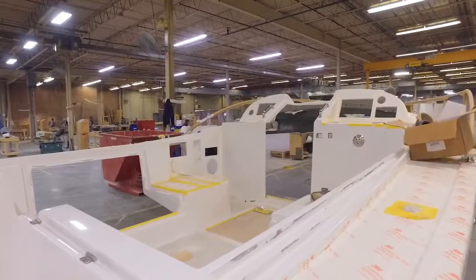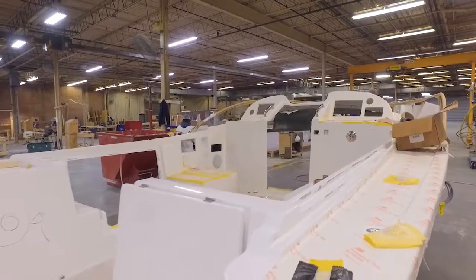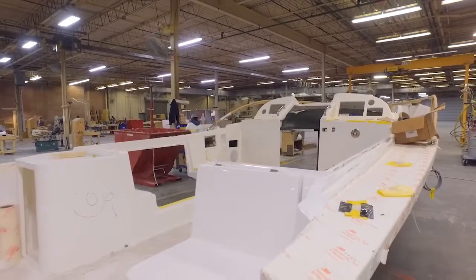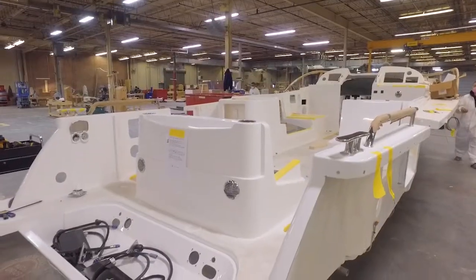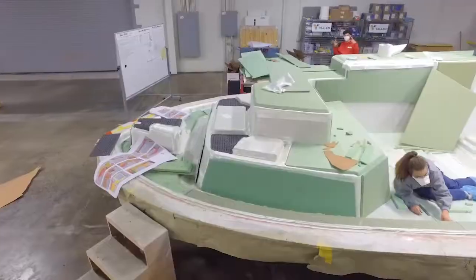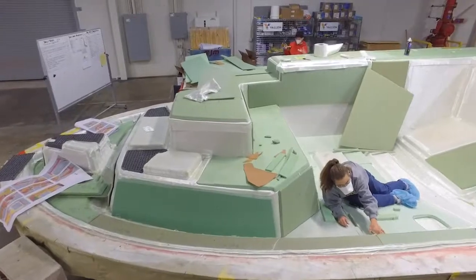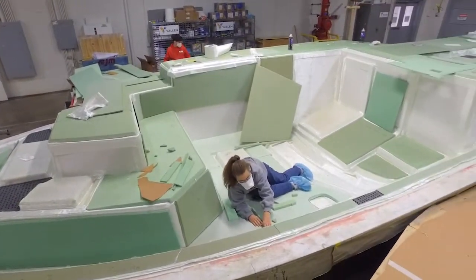But we had a team of people with good boat building background, and we got together and we said, how can we make this happen with the minimum of risk? On the first deck, we had 90% success. So to be able to infuse an epoxy deck on top of a vinyl ester skin coat, we did a lot of lab testing with the epoxy supplier until we're absolutely sure that we would not have a problem of bonding those two surfaces together.